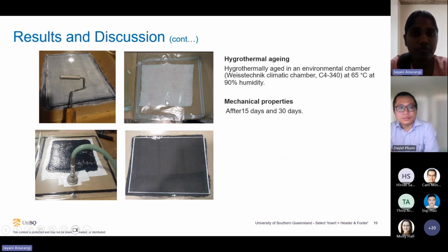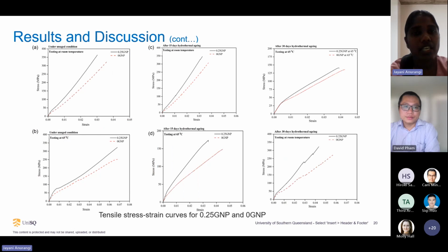properties of the developed composite at elevated temperature at 65 Celsius, as well as I condition the sample in the environment chamber at 65 Celsius at 90% humidity for 15 days and for 30 days, and then I evaluate the mechanical properties. Especially, I evaluate the tensile properties.